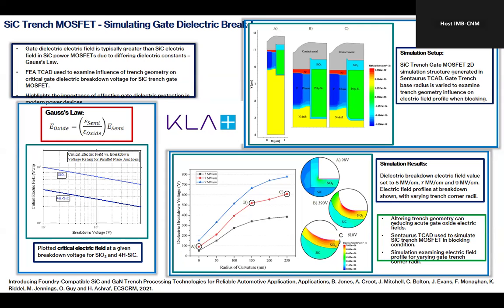Okay, and it's much worse than in silicon, because the high critical electric field strength of these wide bandgap and ultra wide bandgap materials is a blessing, because you get lower on-state resistance as a result of that, and you can dope the epi more highly, etc. So the trade-off between resistance and breakdown voltage is better because of that. Okay. However, the high field strength of the material is also a curse.